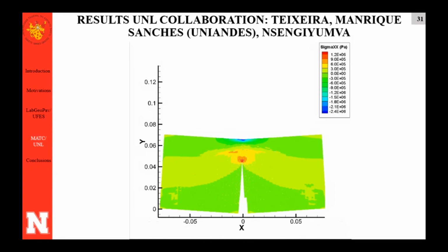So basically I had one question in mind when I came from Brazil. Can I use the nonlinear viscoelastic cohesion model? And which internal state variable should I use in order to account for the rate dependence of the material? And we changed the way we approach the model, because we verified that the phenomenological law that people who use the nonlinear viscoelastic cohesion model usually use is not enough to account for the rate dependence of the materials. By going through a Gaussian distribution function, now the model can account for the rate dependence of the material.